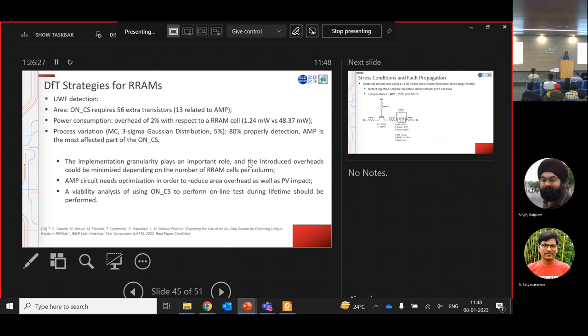Of course, for the implementation of the memory, we don't know exactly what the model of the memristor is, but all these memories, in the design phase, you needed to deal with this cycle-to-cycle variability of the device, because you are going to have device-to-device variability that you are going to cover at time zero. Okay, but you also have this cycle-to-cycle variability of the device, which means that sometimes it's not enough to apply just one set or one reset operation to put the device in the high resistance state or low resistance state. You needed to apply several pulses, okay? And when you apply that, you put your device in a stable region, a stable value in terms of resistance state. Okay, this is implemented in the design phase of the memory.